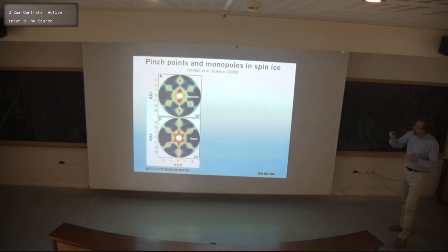And this can actually be calculated. You could imagine setting up this 2-in, 2-out state by Monte Carlo, for example, calculating the Fourier transform, and then you get this particular pattern. So it's very well understood, and these data really do show that we have this manifold of states for a compound such as dysprosium titanate.